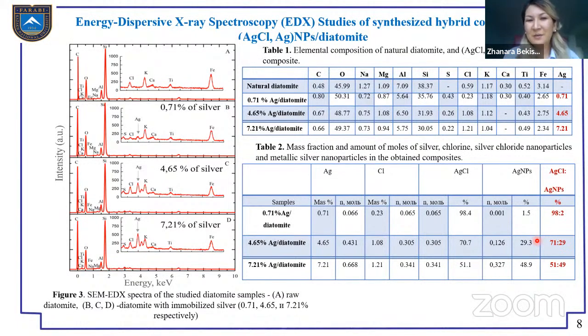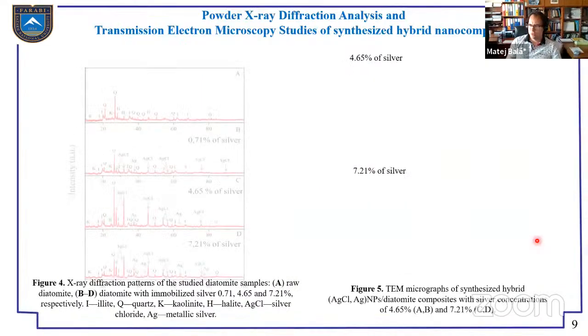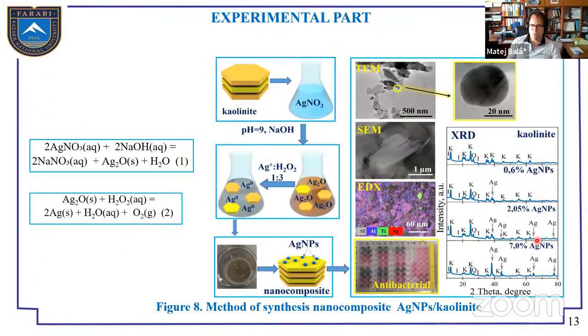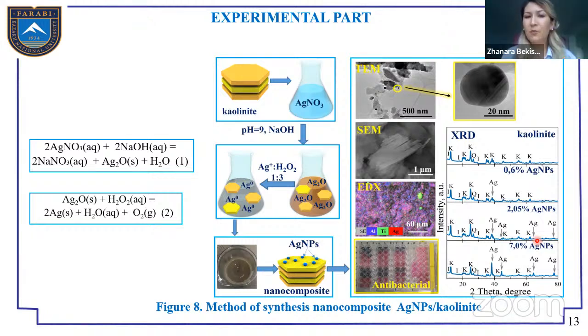All right. So if we go to slide 13, you use the ratio between silver ion and hydrogen peroxide of 1 to 3, yeah? So why exactly was this ratio used? We analyzed the literature, because scientists use different reducing agents, tetrahydroborate and formaldehyde, and the ratio 1 to 4, or we chose 1 to 3 because after that we washed 5 times after reducing, and it is enough to reduce silver.